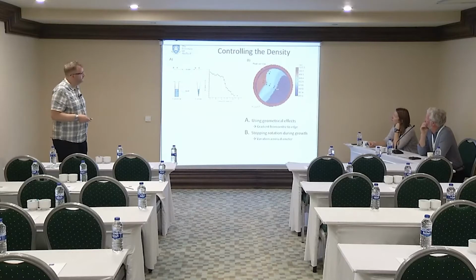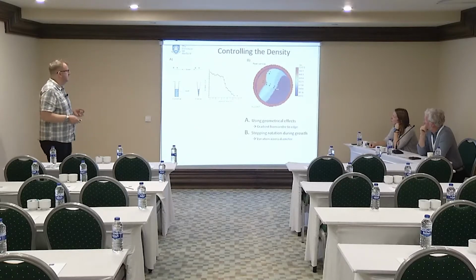We could stop rotation. And if we stop rotation, then we'll get a gradient across the wafer from the side where the source is to the opposite side. So we have a decrease in density going across, or in this case, we're showing this as emission wavelength. The emission wavelength is getting shorter. And so again, there'll be a certain region on the wafer which is good.